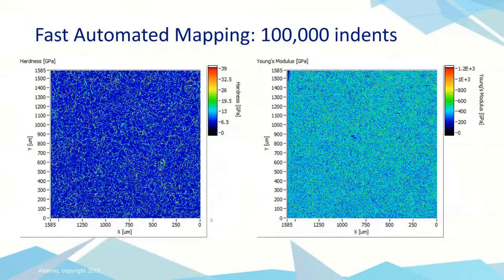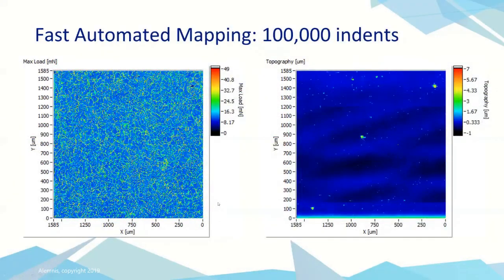So this is the hardness map on the left, modulus on the right. So quite clearly we can see the grain structure. And here we've actually got a map made using the max load values of all of those indents. So it's even better clarity on all of this grain structure and the topography image on the right.